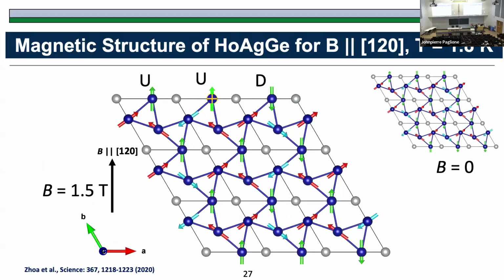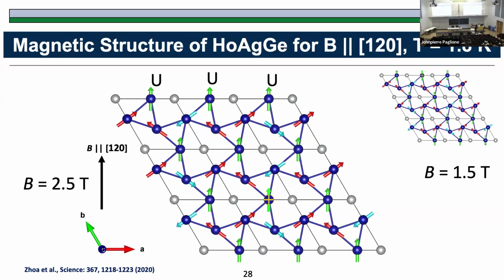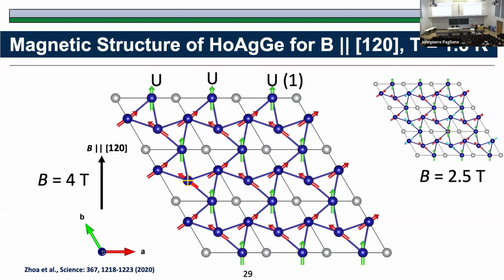So again, these are different states. I call this the UUD state because it's 2 up, 1 down. Then you apply another field. You make all these spins parallel, UUU, and still here the blue atoms are not touched. Then you apply further magnetic field. The blue atoms also become red atoms because they now have components along the B-axis. Then this gets into a different magnetic state, and it becomes extremely difficult for them to be polarized. We measured it maybe even up to 70 Tesla at Los Alamos, and it doesn't saturate there. It keeps growing. So it's a huge anisotropy.